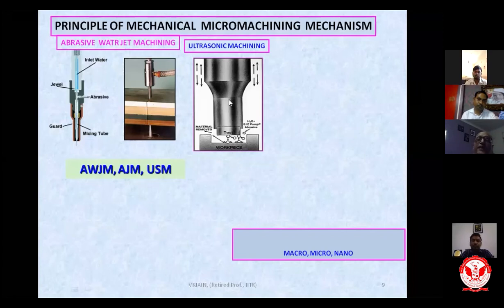Same way, here is the ultrasonic machining or micromachining process principle. This is the tool, and this is the workpiece which is being machined, and you have the slurry. This slurry consists of liquid and abrasive particles mixed with some additives. Now, when you are vibrating this tool, it vibrates at ultrasonic frequency, which simply means around 20,000 hertz, 20,000 times per second. And there are hundreds of abrasive particles hitting the workpiece surface.